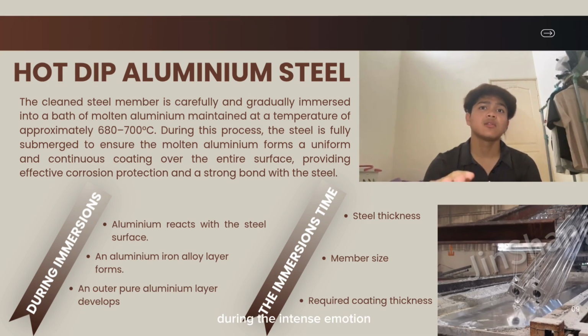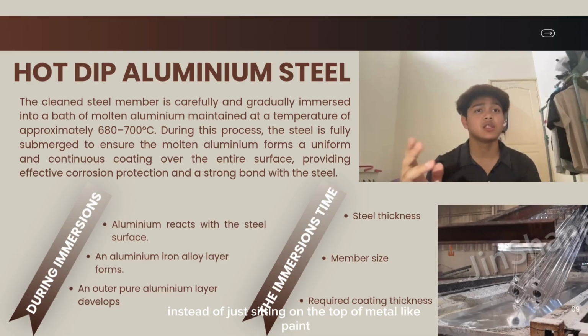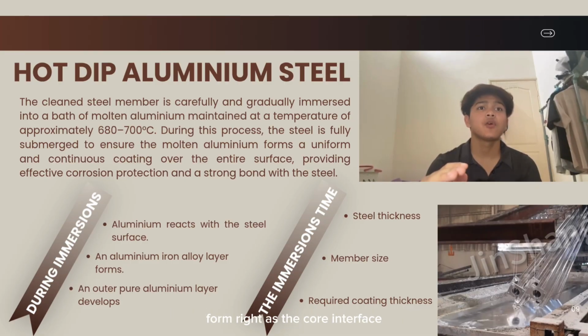During the intense immersion, a profound chemical reaction takes place at the molecular level. The aluminium reacts directly with the hot steel surface. Instead of just sitting on top of the metal like paint, an exceptionally strong aluminium-iron alloy layer forms right at the core interface. As the part is withdrawn, an outer layer of pure aluminium develops over this alloy layer.